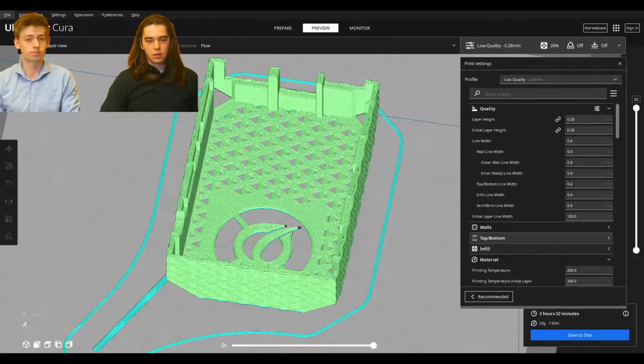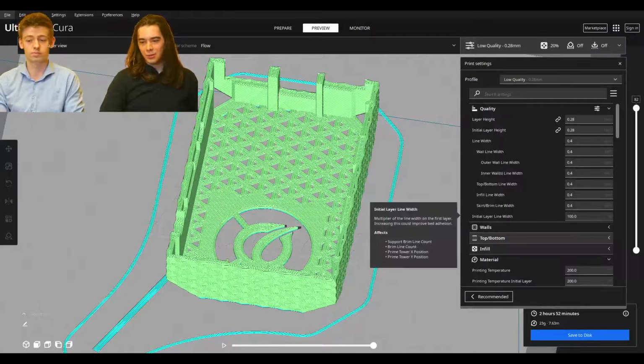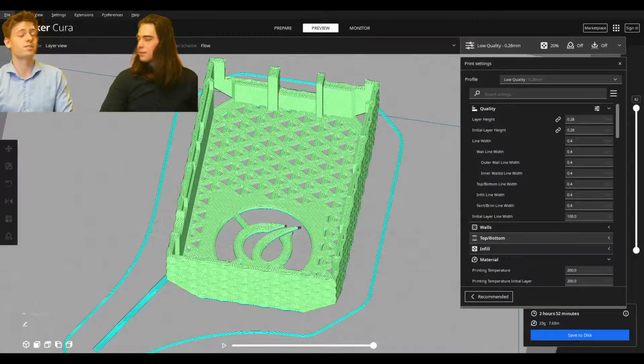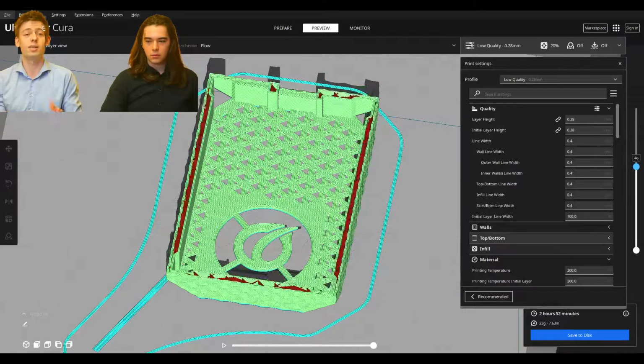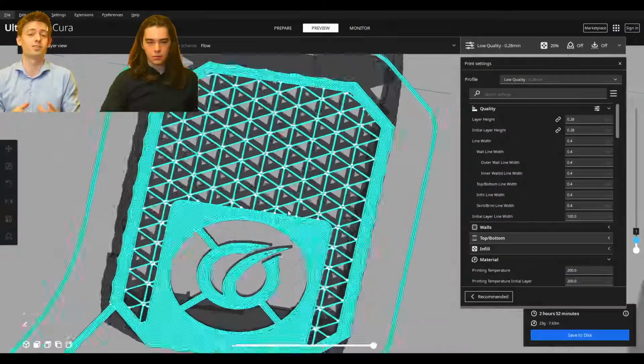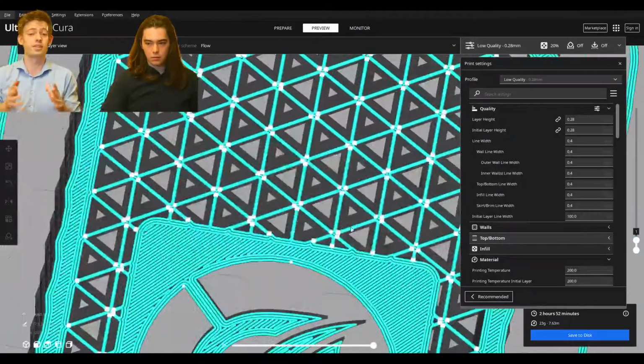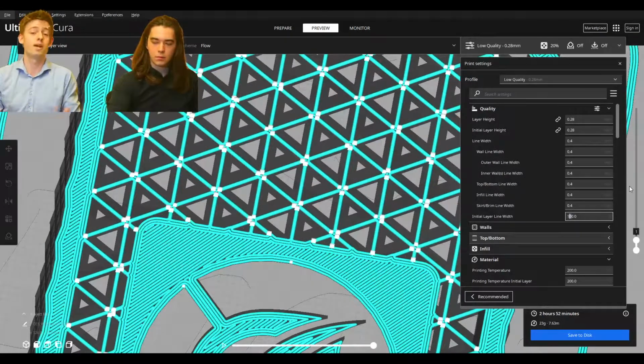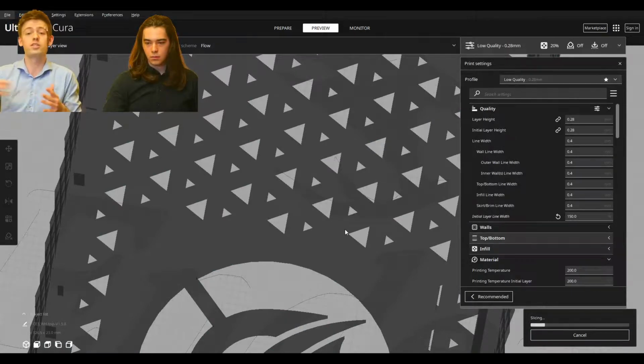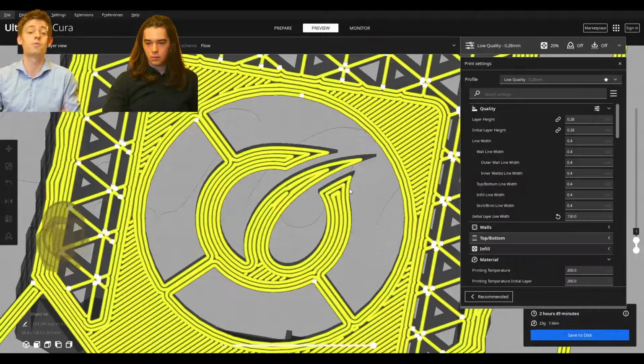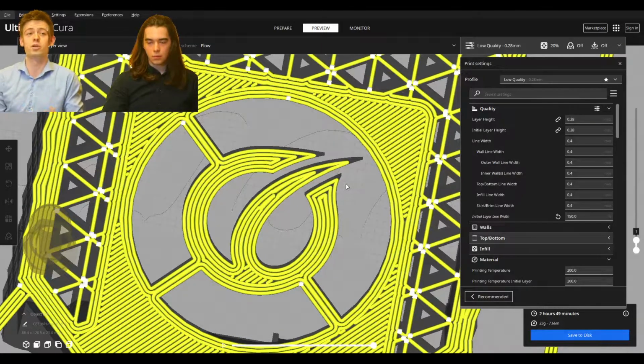Yeah. So to recap, why do we print with wider lines? Wider lines increase the amount of material on your first layer, and that means there's more thermal energy coming out of your nozzle, and that causes the material to stay liquid for longer and adhere better to the bed. I would also say that it reduces the complexity of your first layer, making there fewer points of failure. And it also reduces the sharpness of your corners somewhat, so there's less chance of a 180-degree turn causing peeling on your first layer. Yeah, every line has more surface contact, so every line you print will stick a bit better than with a thinner line width.